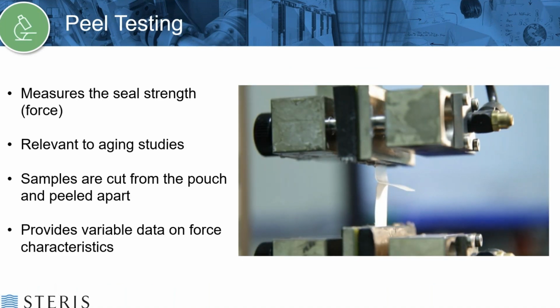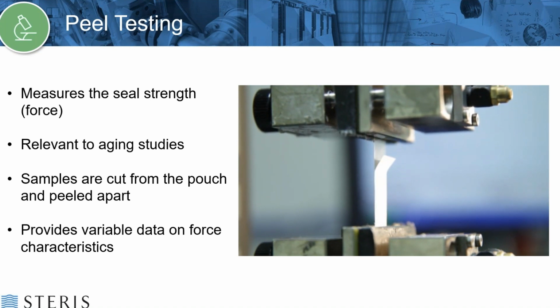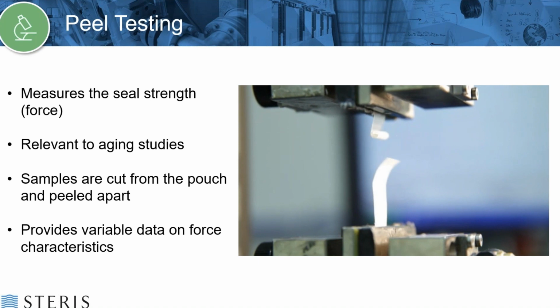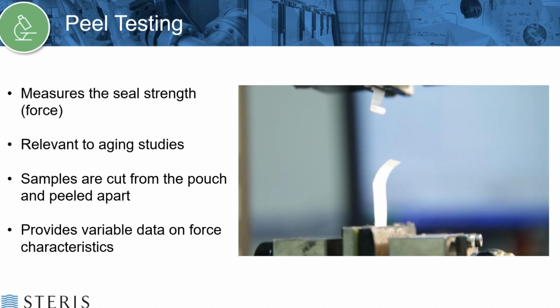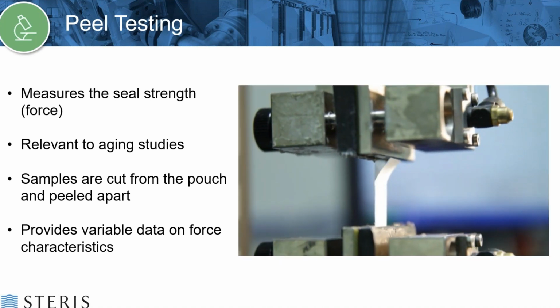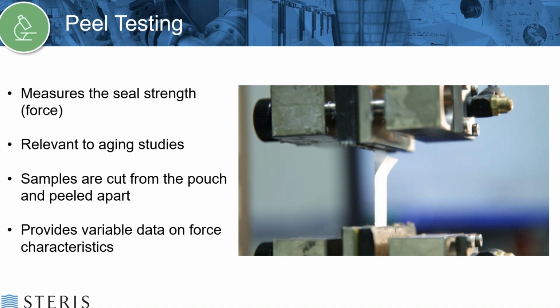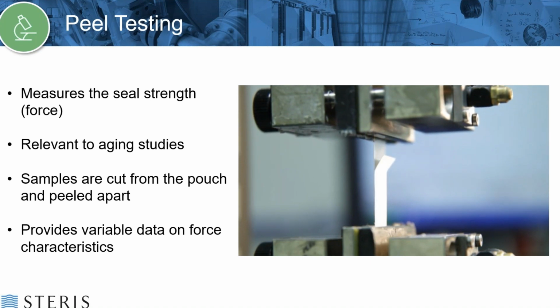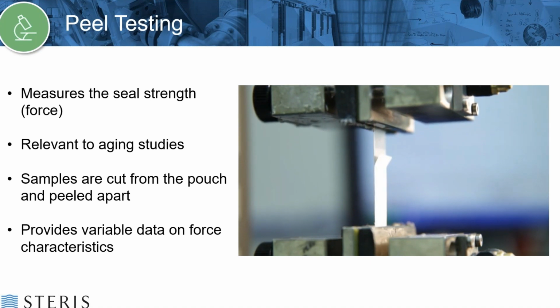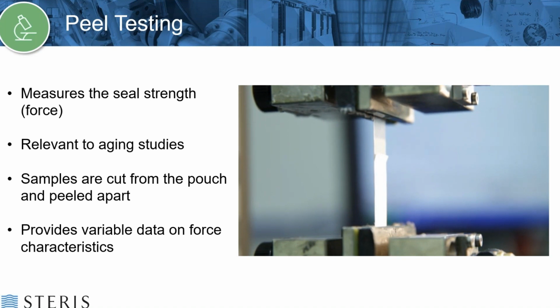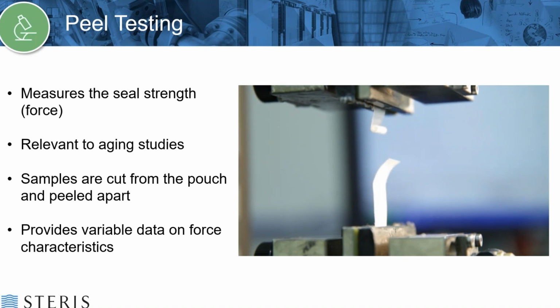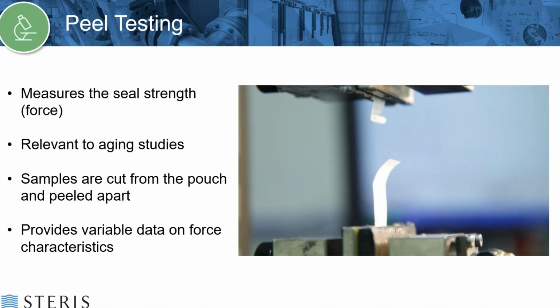And here's peel testing. Again, this is a segment of one of the sides of a package that has been cut out and then pulled and the force measured. So this one's nice because it gives you some variable data, so quantitative data that you can do some statistical analysis on, whereas the integrity tests are more of a qualitative sort of pass-fail type test.